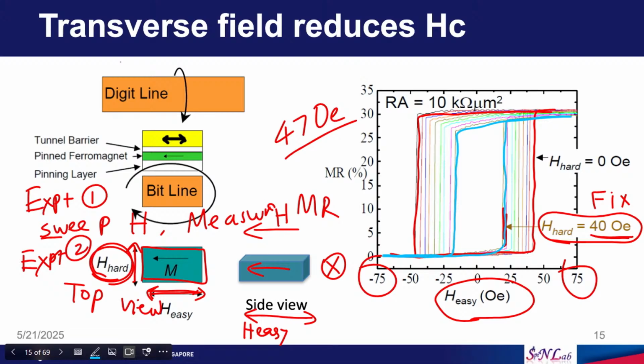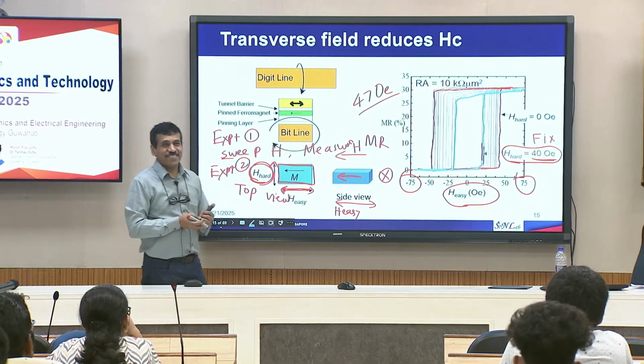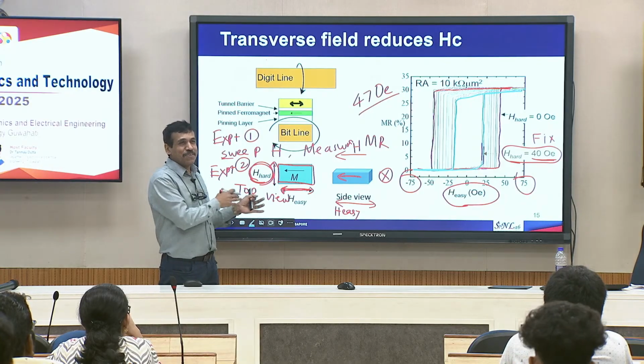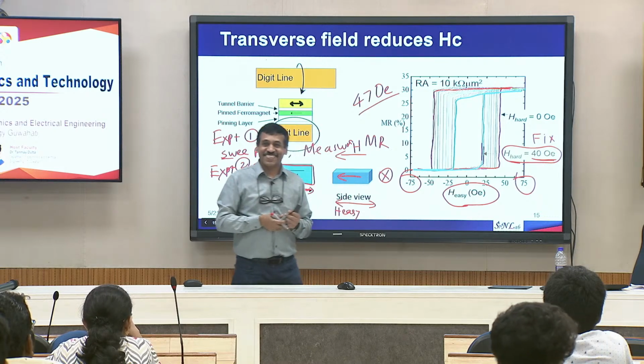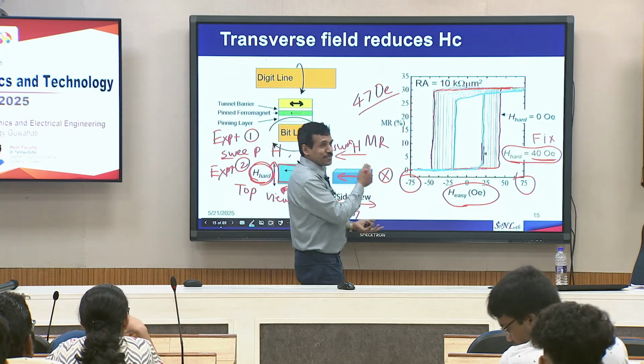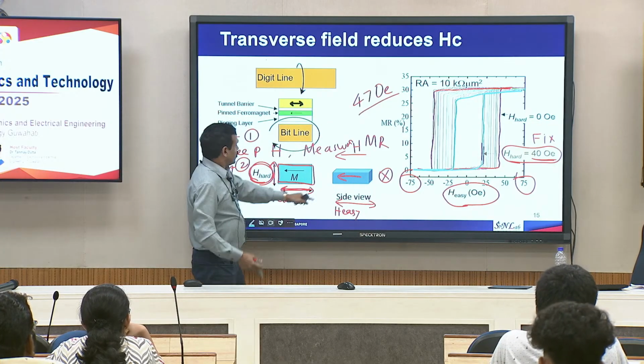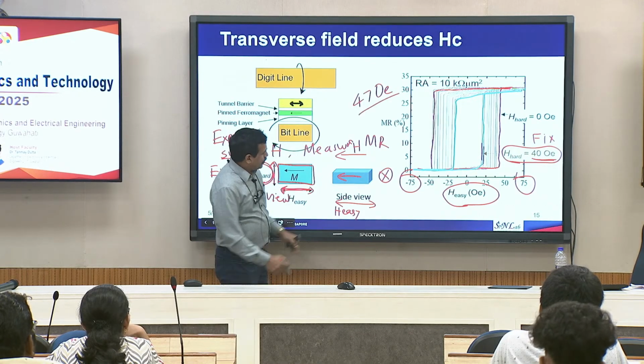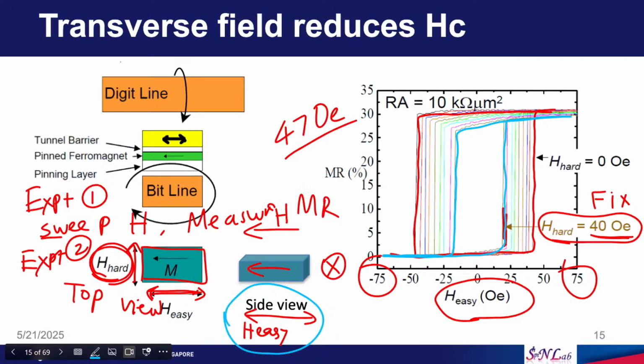So, what is the major difference you see now? Not all questions are tricky, some questions are very simple, so feel free to answer without being scared. It is very obvious, right? Coercivity has reduced. When you measure the hysteresis loop of a sample with only one magnetic field sweeping, you have a coercivity of 47 Oersted, but in the presence of two magnetic fields, easy direction and hard direction, the coercivity has reduced to something like 20 Oersted. That is what you see here.